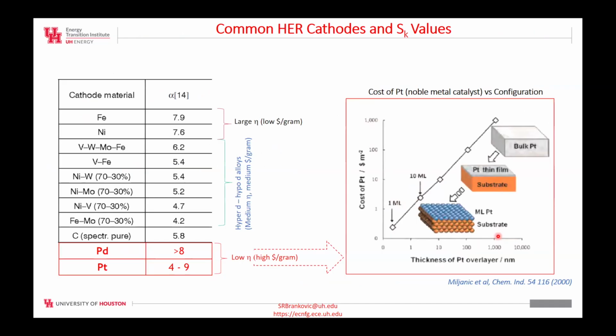So in conventional electrolyzers, which are used for hydrogen isotope separation, iron and nickel are well known, and they require relatively modest overpotentials, and they're relatively cheap compared to the noble metals. Their hydrogen separation factors are on the order of 7 to 8. Then we have Hyper D alloys, which have slightly lower separation factors, but they are also more durable and can withstand longer operation times. And here we fall into palladium and platinum, which are extremely expensive, but they require very low potentials, which means a low energy intensity for operation. And therefore, their cost may be high when you think per gram, but actually their efficiency is very good. So you're not spending too much electricity on electrolysis.